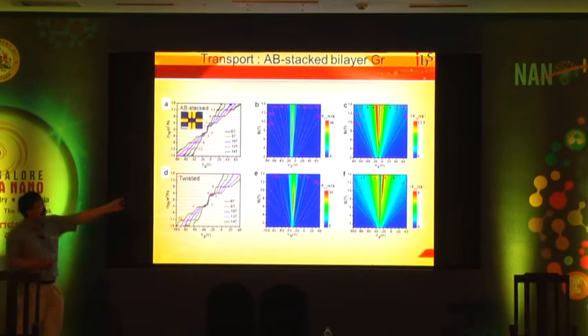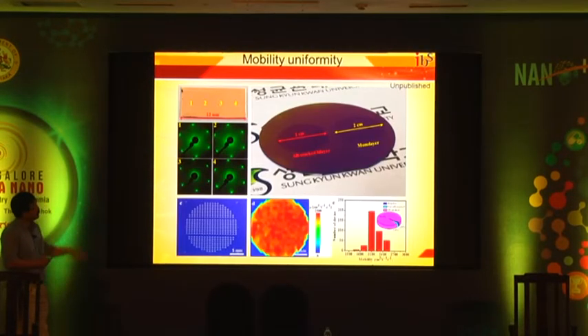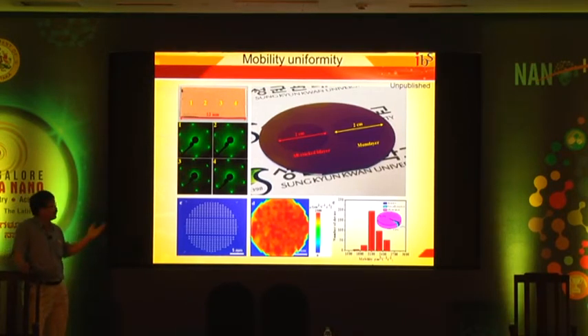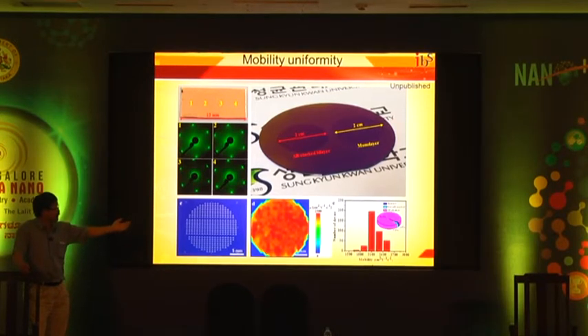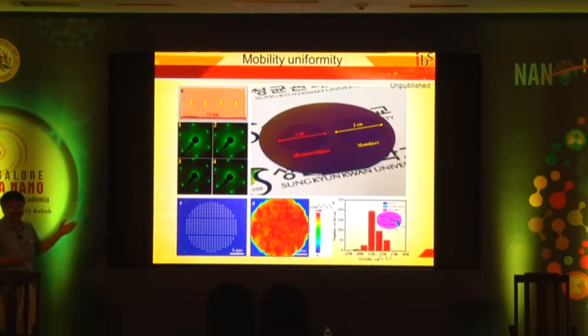You can see these clear Landau patterns in different ways. Now, of course, you can then try to make millions of devices. In our case, we have several hundred devices on the same wafer, and we try to calculate the mobility in each device. You see they are quite uniform. They are mostly from this AB stacking order, although like 5% is still non-AB stacking order. This is an artificially created single crystal bilayer, but I mean, it perfectly works.